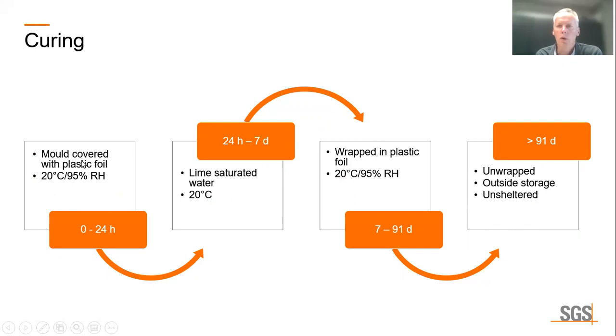After casting, the mold was covered with a plastic foil and put in the climate cabinet at 95% relative humidity. After demolding, it was then stored in lime-saturated water up to 7 days. After 7 days, the cubes were wrapped in plastic foil and again stored in the climate cabinet at 95% relative humidity. And then finally, all specimens were unwrapped and stored outside under unsheltered conditions to be close to practice.